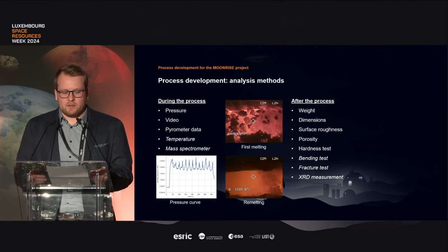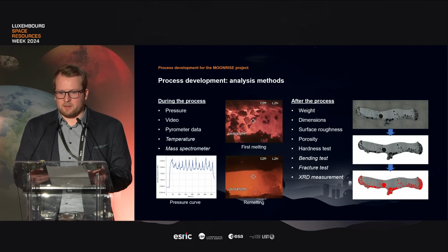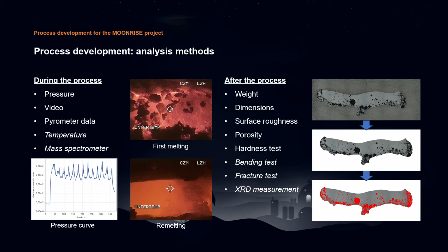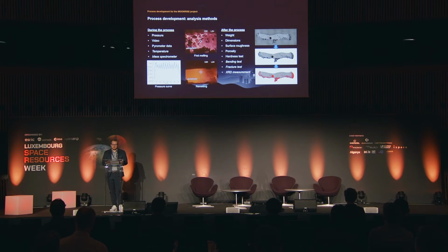And after that, we will produce some cross-sections of these samples, of which we determine the porosity via some image processing scripts, as you can see here in this little schematic. So we have the cross-section on the top, then we remove the background, and then we count the pores. And this particular sample has a porosity of 15%. After that, we also do some hardness testing, which is our only mechanical value. So these samples have a hardness like typical glass.